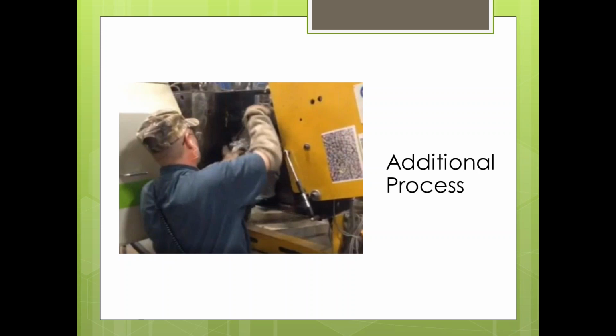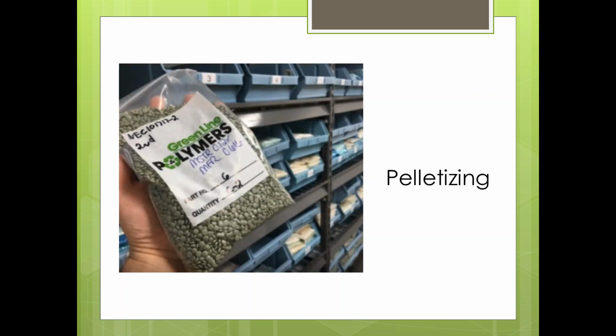So both of those will float on water, and that can lead towards needing some additional processes like this to pull out additional thermoplastics. So what you're seeing here on the screen is actually a pelletizing operation, where we basically melt and push the plastic through various meshes of screens. All thermoplastics melt and are molded at different temperatures. So it's geared towards melting the HDPE, pushing it through the screens, and catching a lot of that additional debris in these screens.